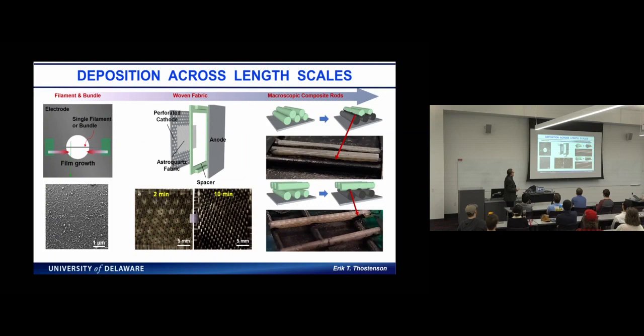And this is just an example where we wanted to show that this is not just raining down. So we did some work where we had a perforated electrode, and you see initially that pattern shows up on the fabric, but at longer times, that network starts to grow as an extension of the electrode. And this is just where we wanted to show the mechanism and visualize this at a larger scale. Here we have rods that are maybe a millimeter or two, and we did the same deposition, and you see that coating starting to grow. And again, what you see here is that coating growing initially on what's in contact with the electrode, but then over the surface. And that's what gives us this really uniform coating.